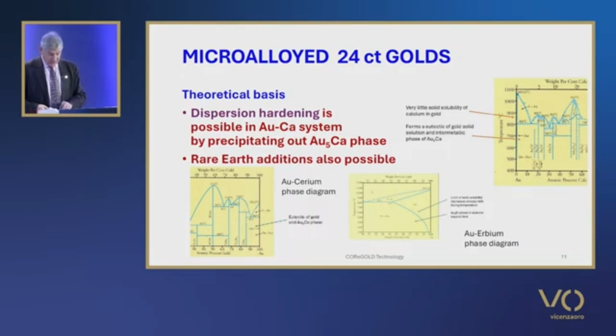reference to the phase diagram shows that there's virtually no solid solution of calcium in gold, and that there is a eutectic comprising 2 phases, gold and an intermetallic compound, gold 5 calcium, which has a high gold content. If this phase is finely dispersed in the microstructure, then we have the basis of a possible alloy system that could provide improved properties through dispersion hardening.